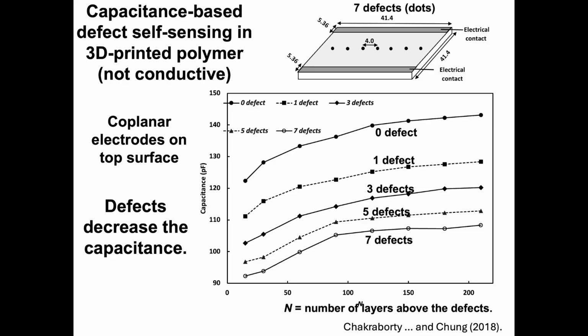So we use capacitance-based defect self-sensing in 3D printed polymer, which is not conductive. And we had 7 dots representing 7 artificial defects placed at certain positions between certain layers. And we measured the capacitance using these 2 electrical contacts, and we were able to figure out the number of defects. Is it 1? Is it 7? And also between which layer the defect is located.